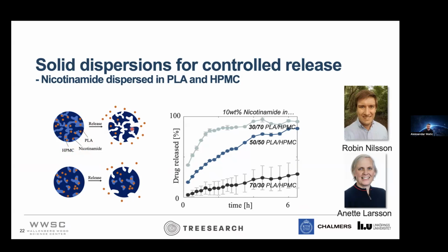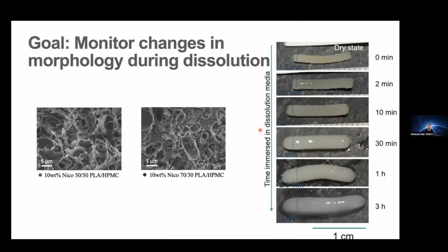And you can see here to the right the drug release response as a function of time. The more HPMC you add, so here we have 70% HPMC, you have much more rapid release. So by altering the ratio between the polymers, you can tune the release time. And the idea here was to have an extended release formulation. And this is work done together with Robin Nilsson and Annette Larsson here at Chalmers, and also connected to the Fiber Competence Center.